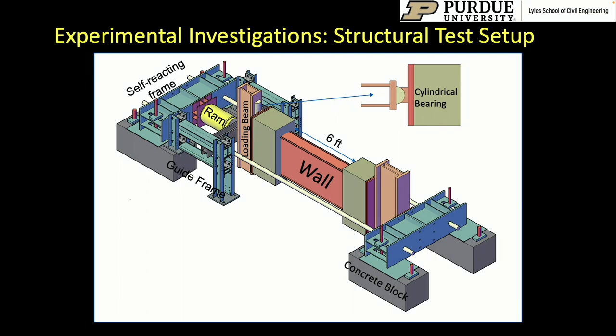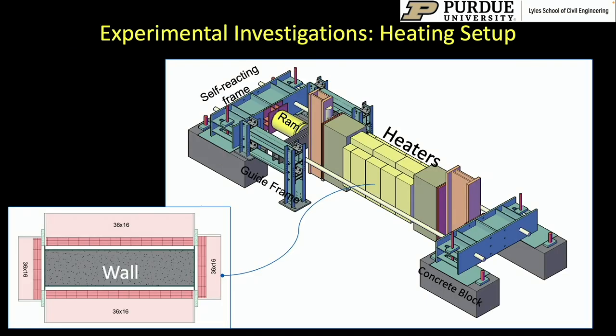This is showing you a structural test setup for the wall. It is being subjected to axial compression using the self-reacting test setup. And then it is covered by what are ceramic fiber radiant heaters, which I can control the temperature versus time response of on the surface of the steel, that are completely covering up the wall and subjecting it to different time temperature curves, depending upon whether it is uniform heating or non-uniform heating.